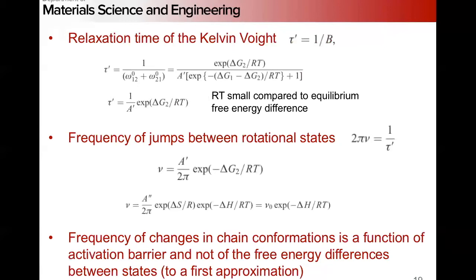And the relaxation time we can use to relate our frequency of jumps between these rotational states. At the end of the day, the big message is that the frequency of these changes in chain conformations is really just a function of the activation barrier, rather than the actual absolute free energy difference between the states. First approximation. And this makes sense, right? If we have a huge activation barrier, even though we have a big lowering of free energy, we're not going to be able to overcome this. So we end up back with something that makes sense.